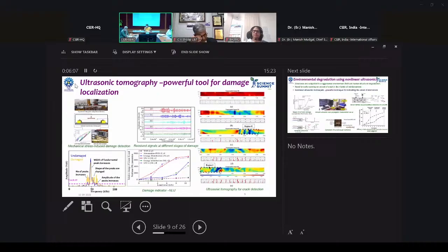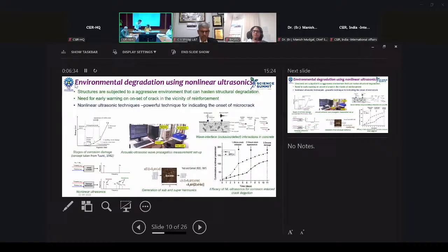The second thing is the ultrasonic tomography. There are many techniques, and even different industries have developed indigenous coding and algorithms by which you can localize the damage in a perfect way, and also see the prognostic behavior of the structure as the crack is propagating. That has been used for the ultrasonic feature, basically the non-linear part.